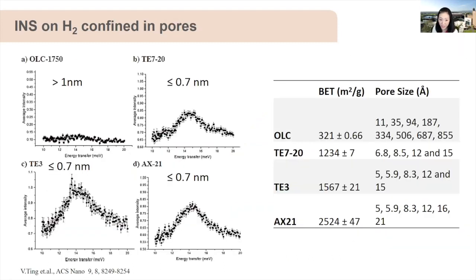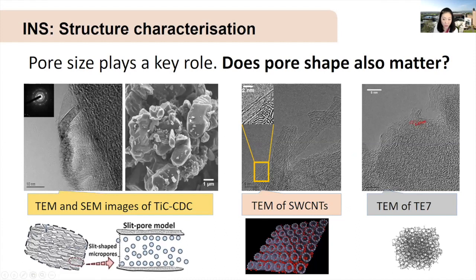And previously, Ting's group has reported the INS investigation on hydrogen confined in porous carbons with different pore sizes, and we can see this onion-like carbon with a pore size larger than one nanometer doesn't have the ability to solidify or densify hydrogen under this condition. But other carbon materials with a relatively smaller pore size all show the solid hydrogen peak at 77 Kelvin. So we know pore size plays a key role in the hydrogen densification process. So we're wondering, does pore shape also matter?